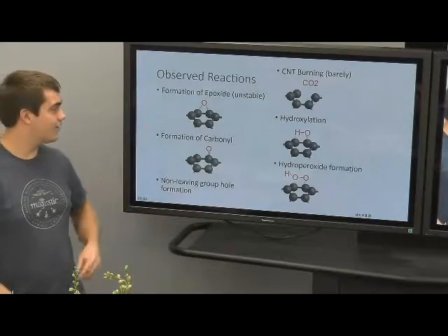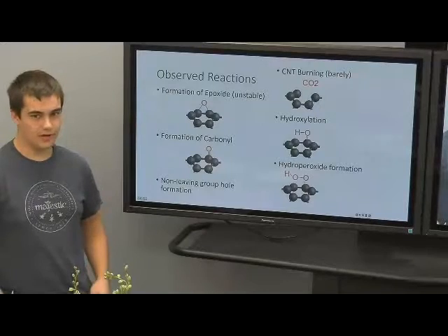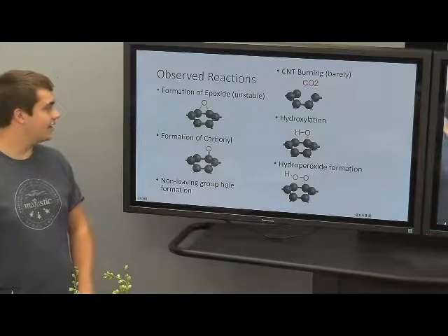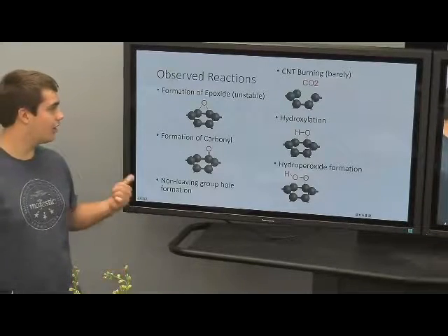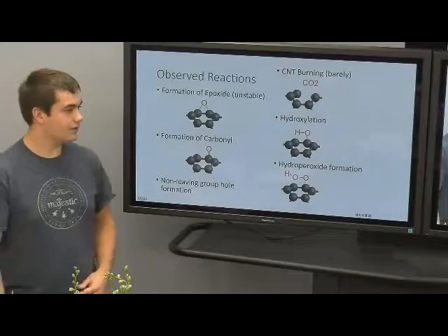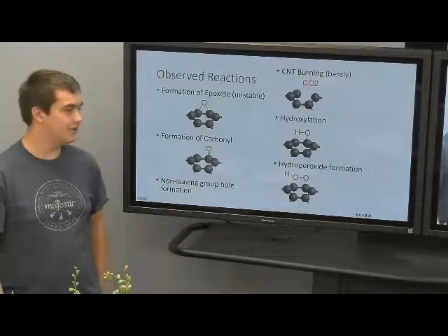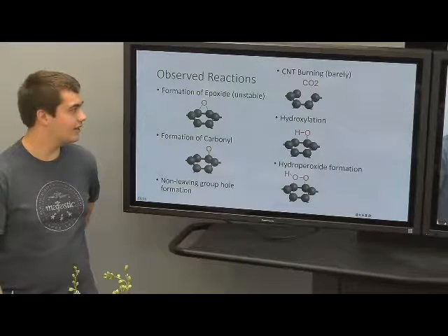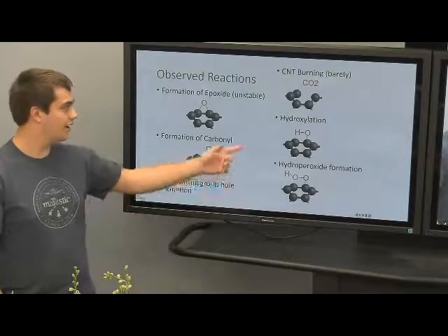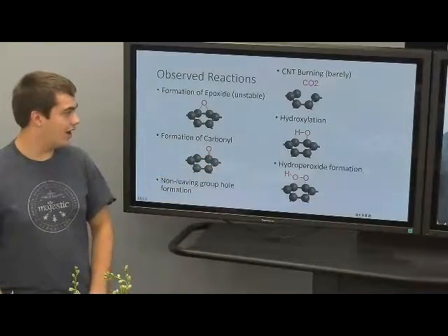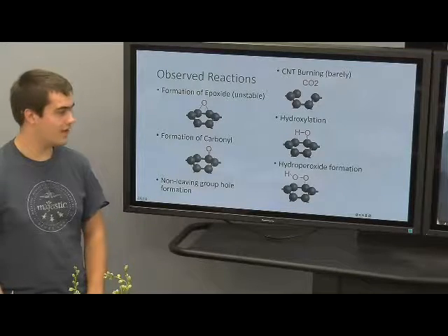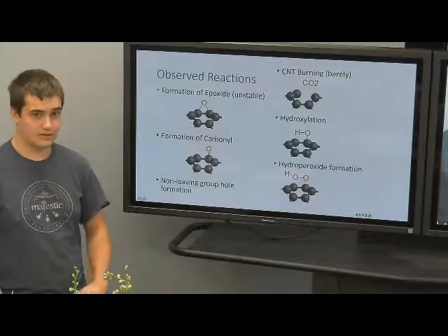We saw an epoxide form, and it was stable for hundreds of femtoseconds, but ultimately it did go to form a carbonyl. We kind of saw maybe a little bit of the burning with the cationic state, but not really anything like I had expected. And then hydroxylation and hydroperoxide formation that I didn't originally expect, but we saw those as well.